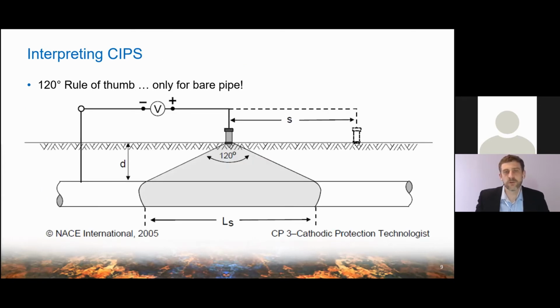So when we take that measurement, what are we actually measuring? Some of you may be familiar with this diagram or one like it. This is from CP3, and it's in the CIPS section of that course. And this is what I'm calling the 120-degree rule of thumb. So here I have my voltmeter, here's my reference electrode, and imagine shining a flashlight, a wide beam flashlight, down from the reference electrode, 120 degrees, and then it shines on the pipeline.